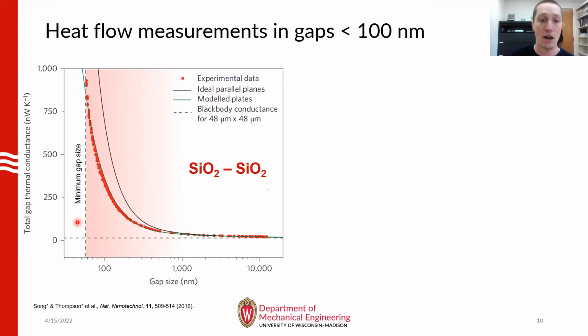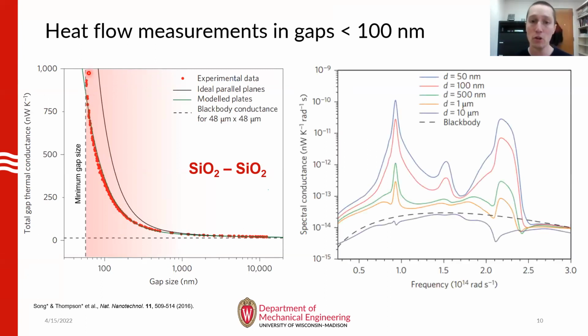Okay. Now, these experimental results also agreed quite well with our fluctuational electrodynamics formalism, where the predictions of that FED framework are captured by the solid green line here. Okay, so we do get good agreement. Now, the theoretical plot on the left is the computed spectral conductance between these two silicon dioxide surfaces as a function of frequency. And this is done for various values of the gap size. So for the smallest gap size that we simulated, 50 nanometers, you see that you get these large enhancements in conductance in 2 spectral regions, one here and one over here.